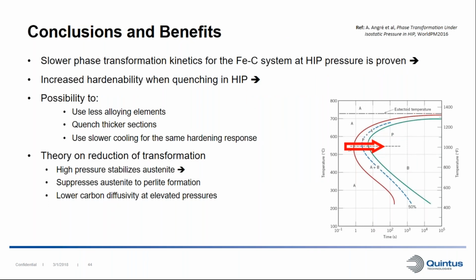So the conclusion from this study was that we can actually affect the phase transformation kinetics of a steel with HIP pressures. What it means is that we get increased hardenability when we're quenching in the HIP. This makes it possible to either use less alloying elements in your material and get the same quenching response, quench thicker sections and get the same hardening response, or just cool slower to get the same hardening response. The theory of this reduction of transformation is that the high pressure stabilizes austenite, so it suppresses the austenite to pearlite transformation. There's also a contribution from lower carbon diffusivity at elevated pressures.